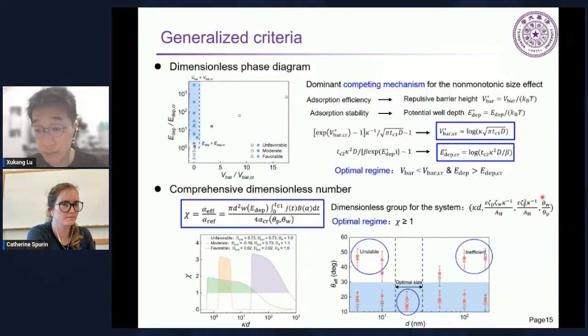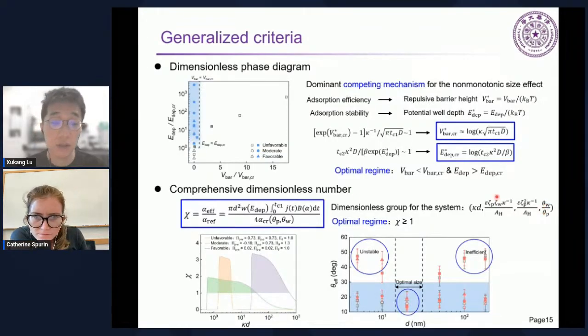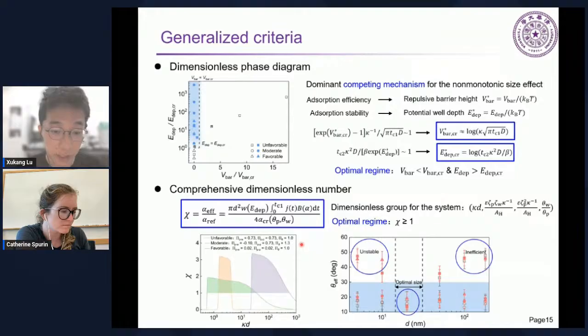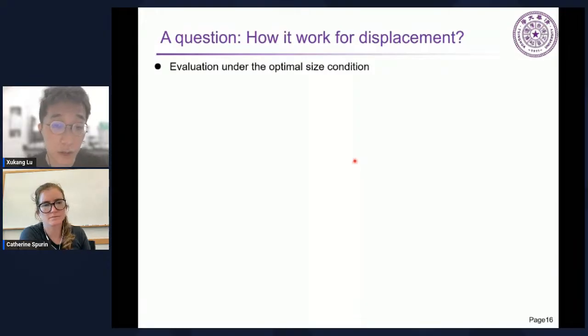With any of the 3 dimensionless parameters fixed, we can determine the remaining one. You can see physicochemical properties and also wettability conditions. So it is a relatively general criterion. And we have validated it regarding the optimal size prediction against many different experimental systems. And with all this, we start to think about how it works for displacement in porous media. It seems that we have obtained all the optimal conditions, but actually many factors have still not been considered. So let's first evaluate it under the optimal condition.